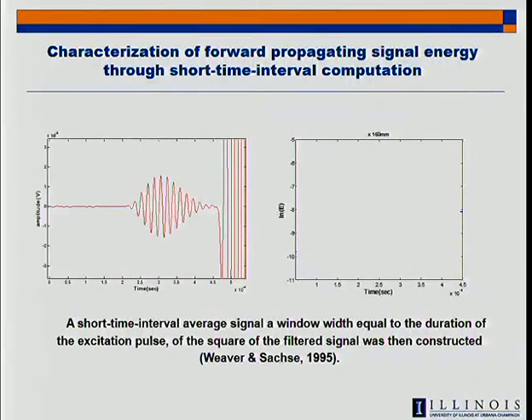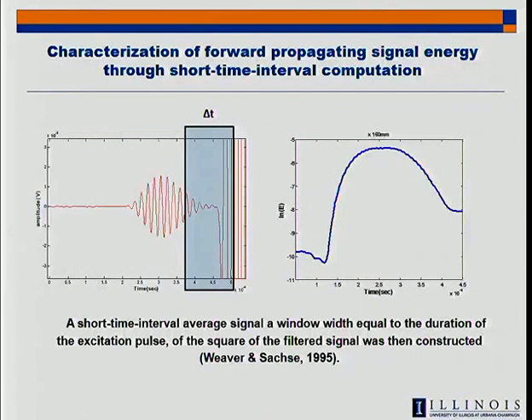So how do we characterize the amplitude? We can do these plots and get a color, but it would be nice to quantify them. So one thing we can do is get a quantity of the amplitude, the energy of the signal. Now, this is the acoustic wave that's coming. It's not useful for us. This is the wave we want to characterize. So we could just measure the peak amplitude at one point and say, oh, it's so many volts, and that's its energy. But rather, we found a better way to capture all of the energy more consistently: we have a moving window, and we move along and integrate that signal and see how much area is under that curve. So as we move along, we see this energy content, and we see these curves.